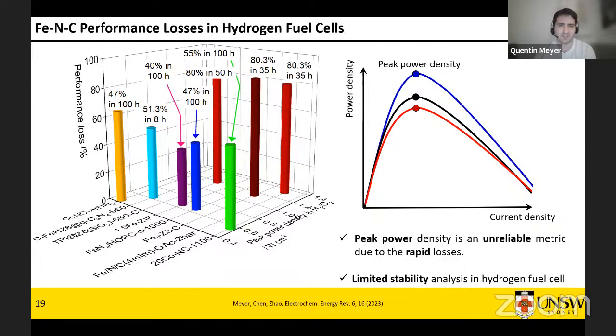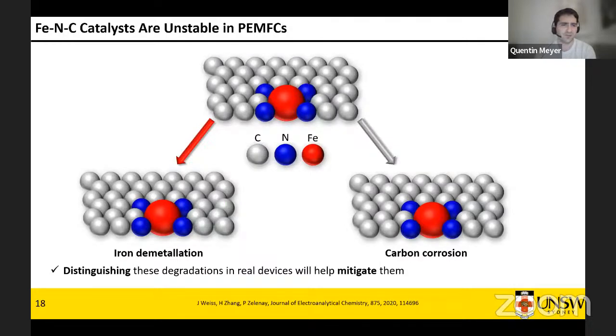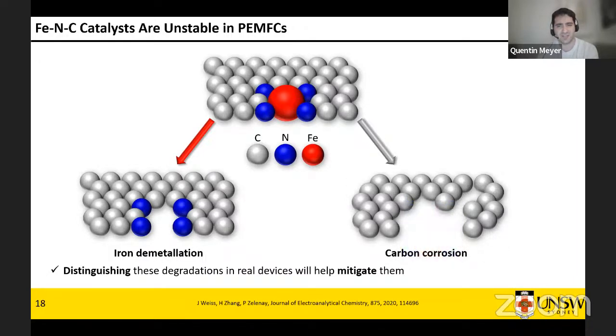And there as well, because it's so unstable, there is very limited analysis in fuel cells, with most groups, as I say, citing papers from about 15 years ago. So the two main reasons the catalysts are unstable is you have what is called iron demetalation. So literally iron active sites leaching out because they're not physically stable. And the second problem is we use amorphous carbon, which is quite sensitive to corrosion. So as corrosion happens, you first lose some carbon, and then you would even lose your active sites because they just physically detach. And figuring out what's happening in a real device will help you mitigate the problem.